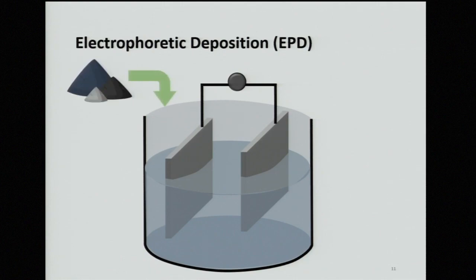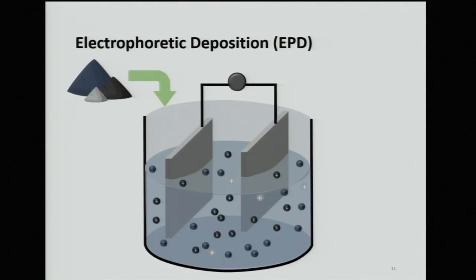Now, within this liquid, we place the lithium-ion material, the conductive material, and in some cases, a binder. And we mix vigorously to make sure that we have a very well-mixed solution. Now, we actually call it a suspension at this point because there are powders in suspension. And in suspension, these powders develop a charge. And whether they're negative or positive depends on the material itself, and it also depends on the liquid that we're using.